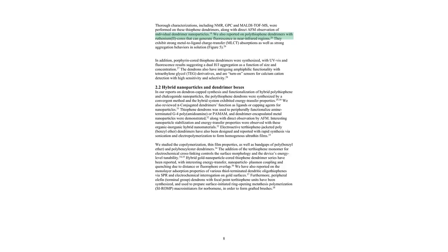Using techniques like AFM, or atomic force microscopy, they were able to directly observe the individual dendrimer nanoparticles. They further functionalized these structures, for example, by placing a ruthenium-2 complex at the core, which created a dendrimer that could fluoresce in the near-infrared region.